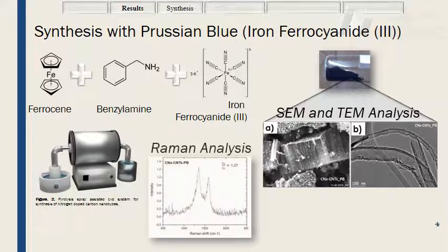In the Raman spectra, a considerable increase can be seen in the D peak with respect to the G peak, which indicates a number of defects in the sp2 network, possibly attributed to the presence of nitrogen in the formation of the doped nanotubes.